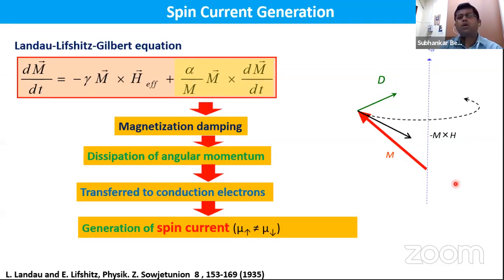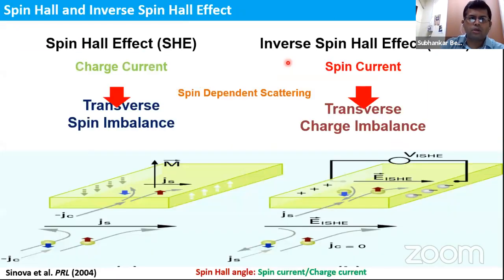Now, how do you generate spin current? Many people who are not working in the field sometimes feel that charge current is the movement of electrons, so spin current is really the movement of spins. The answer is no, because it's basically the flow of angular momentum, spin angular momentum, and you can say dissipation happens from one side to the other. That is how you generate a spin current, and you can achieve that using ferromagnetic resonance in a material, where you can write the Landau-Lifshitz equation in this form. These slides are kind of repetitive. I'm sorry, Sunil, but thanks to you for having explained it.